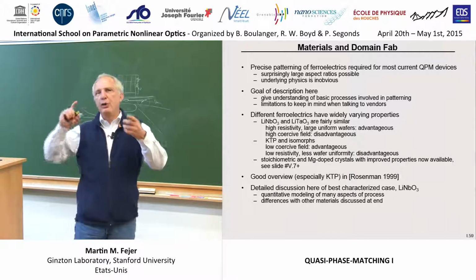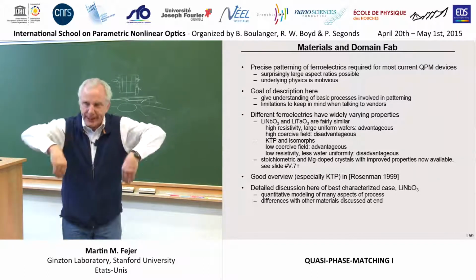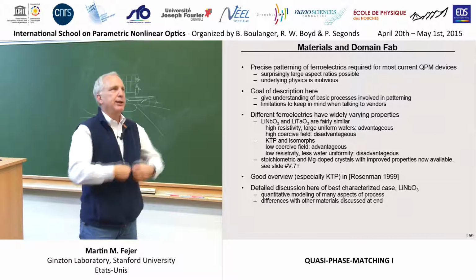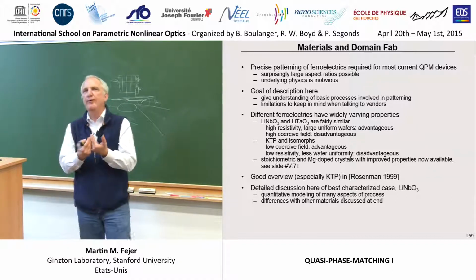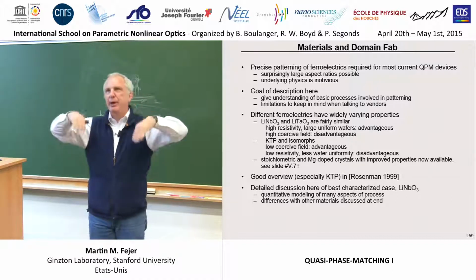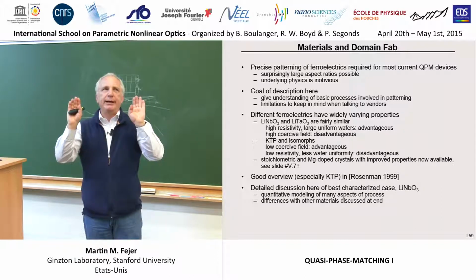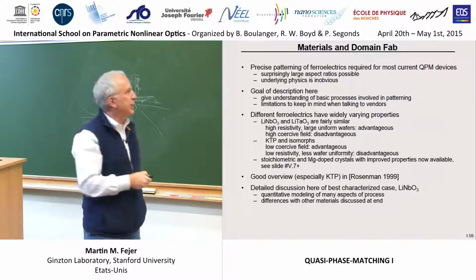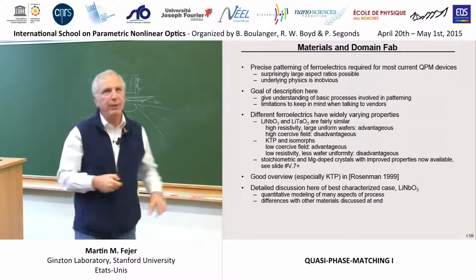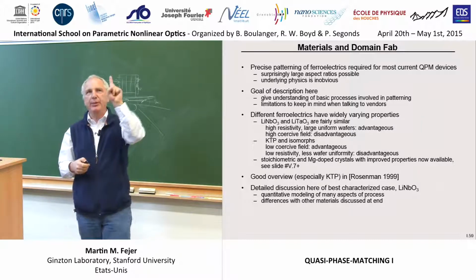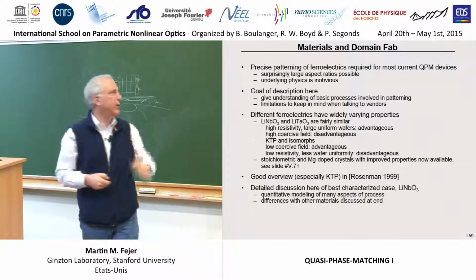Just like there's a coercive magnetic field that you have to exceed to flip a magnetic domain, there's a coercive electric field that you have to exceed to flip an electric domain. That's a pretty big field in these materials. About 20 kilovolts per millimeter you need to apply to make an up domain want to be a down domain.